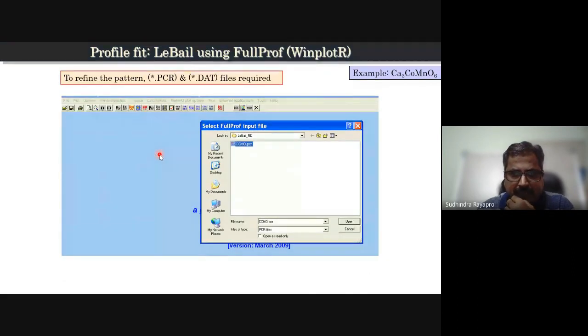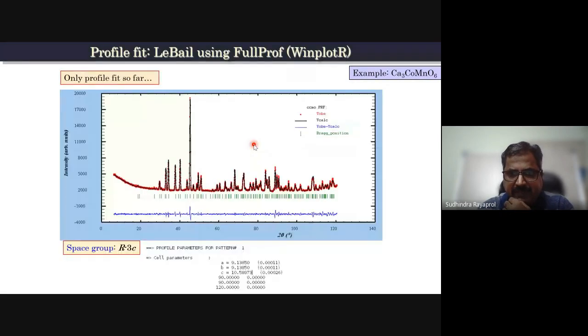Once you have the PCR file, you can call the PCR file, and if you have the DAT file of the same name, it will run the program and do the Le Bail fit. At the end of the fit, the space group which you have chosen is correct, as it fits the entire spectrum. Our cell parameters are correct because all our peak positions are matching, so there is no peak which is not indexed or not fitted. So right now we have a correct space group, correct cell parameters, and certain instrumental parameters which we have fitted using the Le Bail fit.